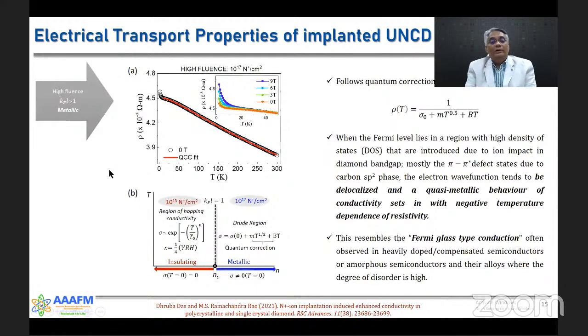When you come to the films implanted with higher fluence, we use the quantum corrections to conductivity model, the QCC model, to explain the process of conductivity, with a nice fitting of the entire data from room temperature down to the lowest possible measured temperature using the QCC model. And what we conclude is the conduction is like a Fermi glass type conduction often observed in heavily doped compensated semiconductors or amorphous semiconductors.